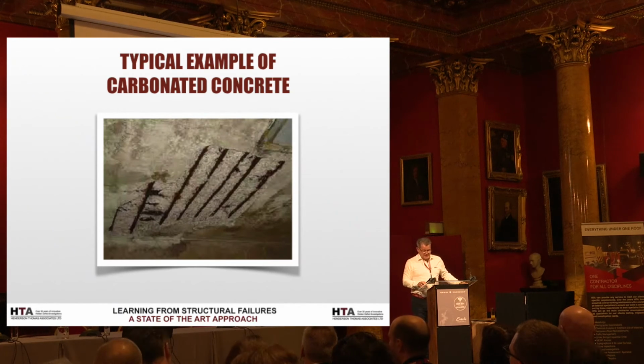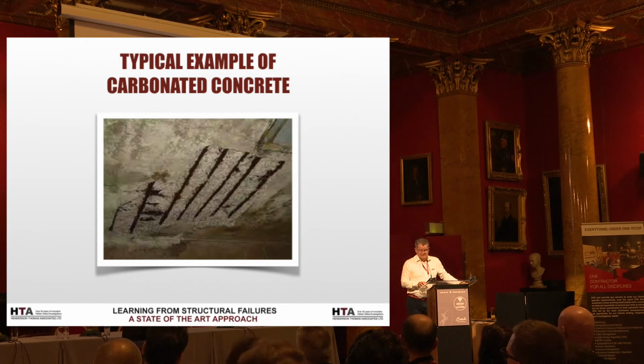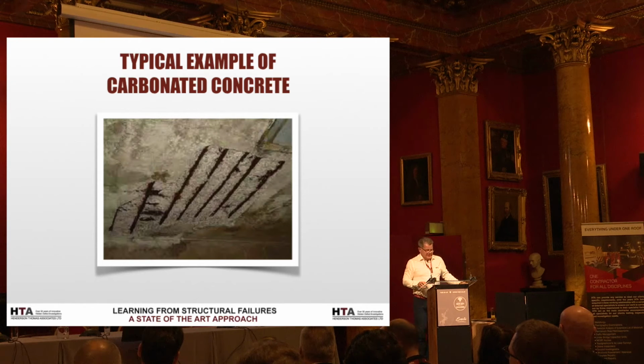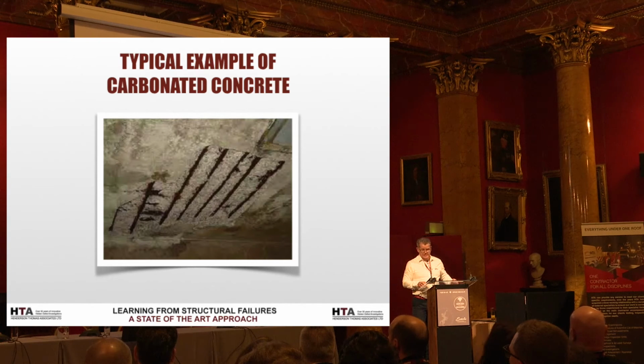People have asked me over the years, can you give us an idea, looking at a piece of concrete, is it carbonated or is it chloride ingress? It's very difficult because there's always one that's going to come along and bite me on the bum, but generally what you tend to find is carbonated concrete and the corrosion that you see with it is normally with bars that have low, restricted cover. They haven't put in the proper formwork or spacer blocks to ensure that the concrete has enough cover.